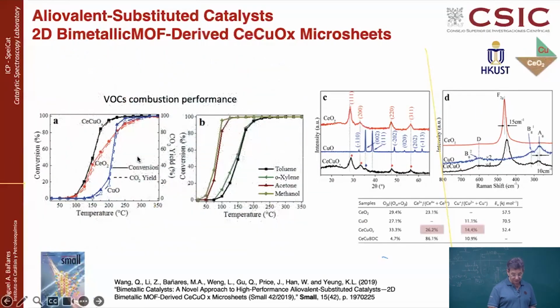And when you look at the performance of this material, you are getting very good conversion for the combustion of toluene. Here you are comparing this metal organic framework derived material against the same material without copper, and again you see a significant increase in performance. And down here you have a comparison with only copper oxide. All of them are active, all of them behave well, but the mixed system behaves significantly better, and we are talking here about some 50 degrees better, which is a lot.